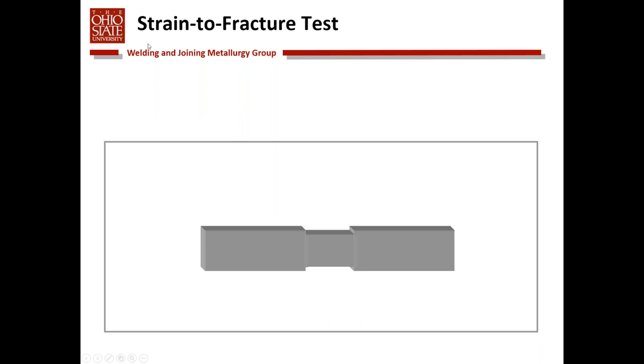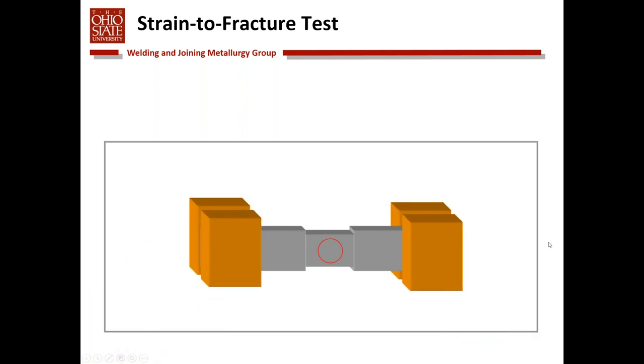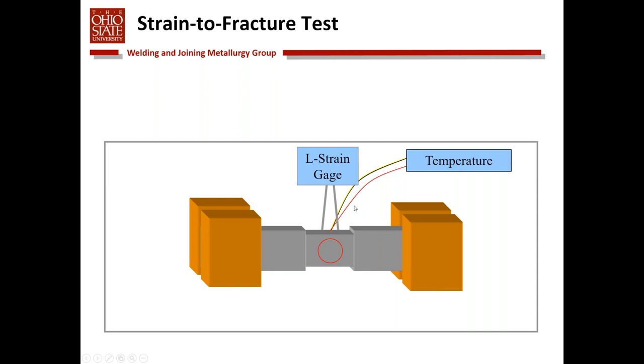So our approach to this, we actually looked at a lot of different tests to study ductility dip cracking, including the varestraint test, but we ended up developing a new test called the strain to fracture test. It's a Gleeble-based test, so we've got a dog bone shaped sample. We put a spot weld in the middle of the gauge section of this sample, and we do that to make the microstructure within this spot weld uniform, which increases the reproducibility of the test sample. After making that weld, we condition it so that we've got a smooth, flat surface. We put that sample in the Gleeble. We attach a thermocouple, obviously.